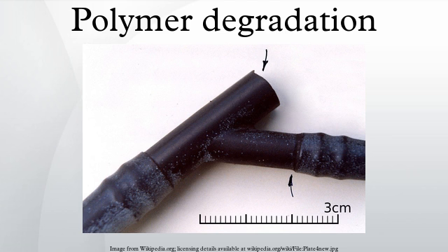For example, polyethylene usually degrades by random scission, that is by a random breakage of the linkages that hold the atoms of the polymer together. When this polymer is heated above 450 Celsius, it becomes a complex mixture of molecules of various sizes that resemble gasoline. Other polymers like poly-alpha-methylstyrene undergo specific chain scission with breakage occurring only at the ends. They literally unzip or depolymerize to become the constituent monomers.